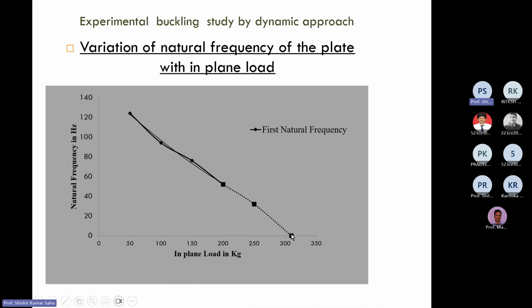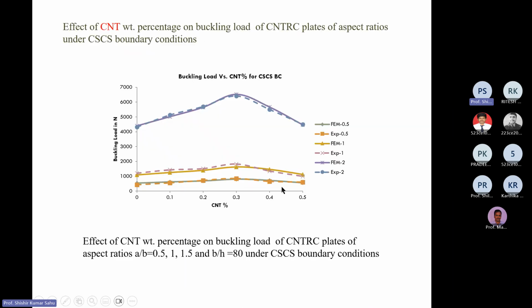Then we extrapolate the point at which frequency is 0; that load is called the buckling load by the dynamic approach. This is in fact recent work, some of which is still ongoing. This is the buckling load for the nano composite with different percentages of CNT: 0.1, 0.2, 0.3, 0.4, 0.5. The buckling load increases up to 0.3% of CNT, then decreases. Decreasing means the possible reason is that the mixing is probably not proper. So it becomes difficult when you go on increasing the percentage of CNT.